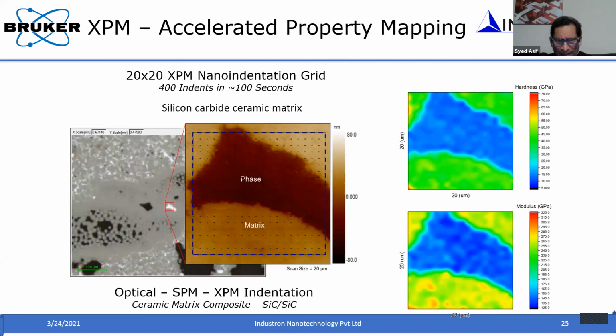Okay. So with that, this is a typical example for a silicon carbide ceramic matrix. This is kind of an aircraft material. And the important aspect is that we wanted to map the properties at a larger scale as well as at a smaller scale, down to one fiber. This is a silicon carbide fiber in a silicon carbide matrix. So to understand how the property changes from the fiber to the matrix interface, we were able to do that. We were able to do a number of indents, not only at room temperature, but also at higher temperatures. I think in the later part of my talk, I may have one slide showing the measurement response at higher temperature, from like 800 degrees C.